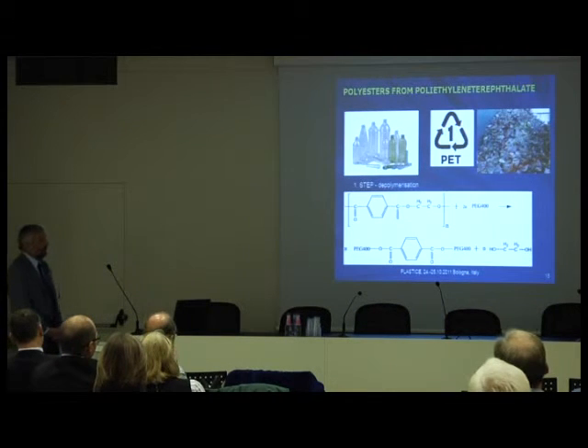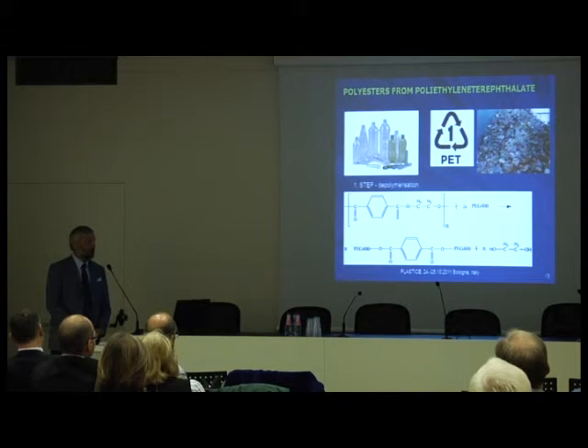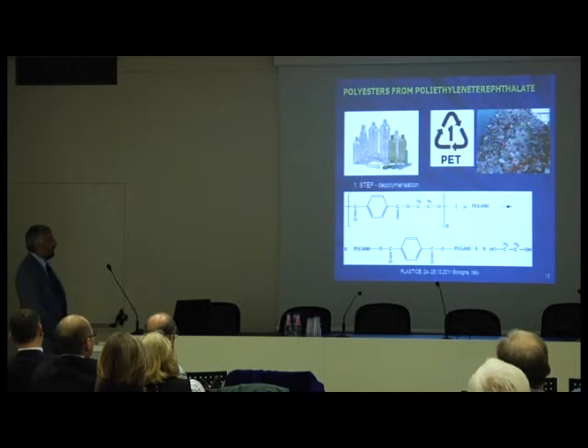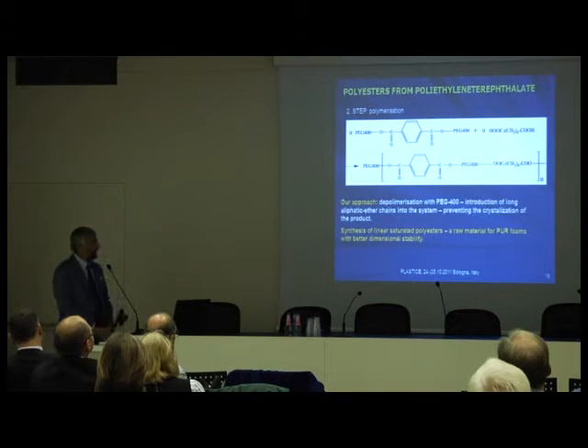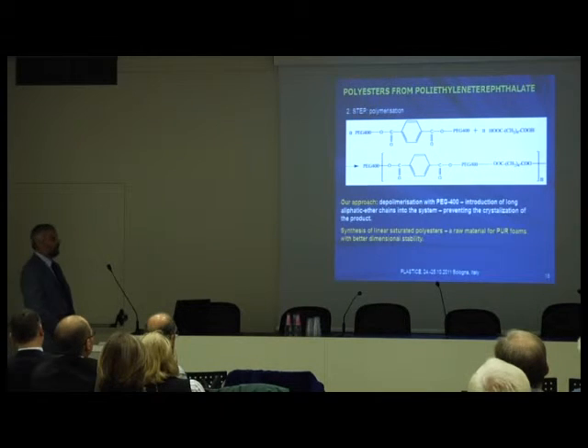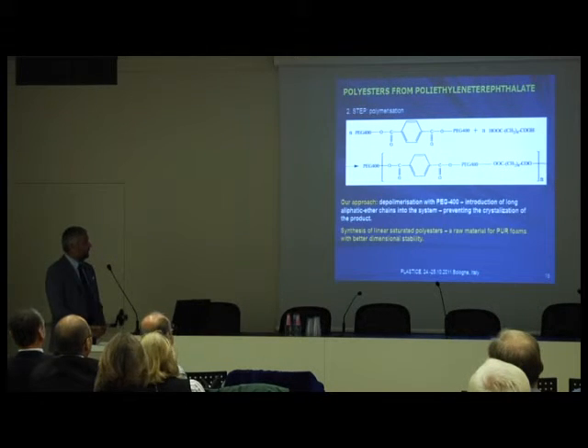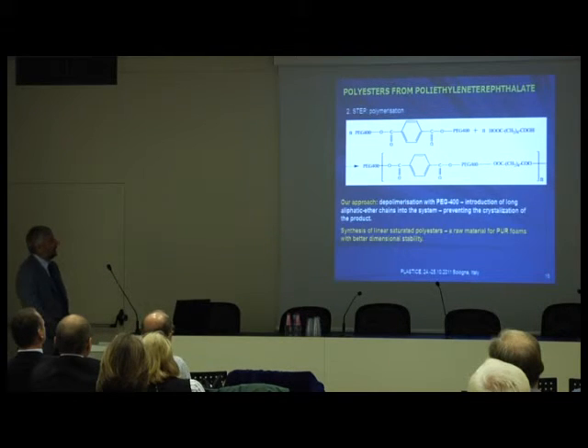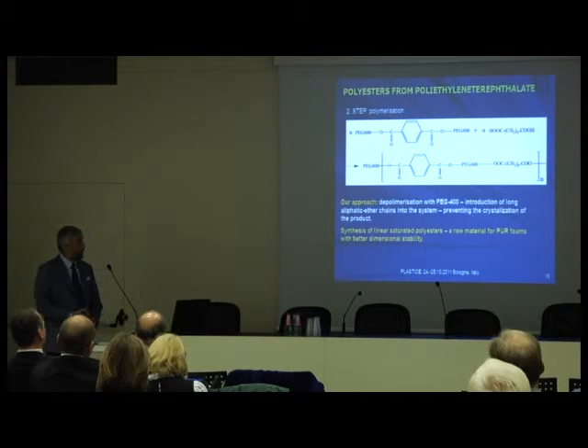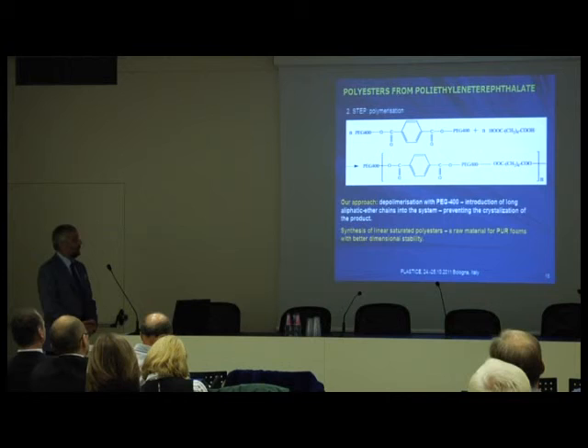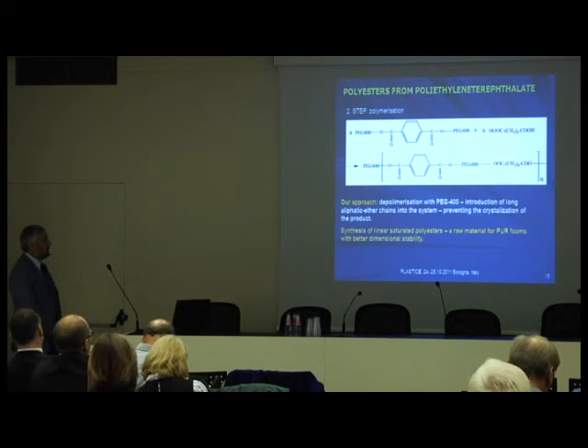On the other hand, we found out that when we use this polyester from the liquefied wood for the polyurethane production, we need something else to add. So we also did polyethylene terephthalate depolymerization and prepared another polyester. Again, we had some improvements in this process, because with the usual depolymerization with, for example, ethylene glycol, you could easily get some crystallized product. We used polyethylene glycol 400 for this depolymerization process, and it was a big improvement. First of all, the product was liquid. Second, it was already a long polymer chain, which is favorable for dimensional stability in polyurethane foam.